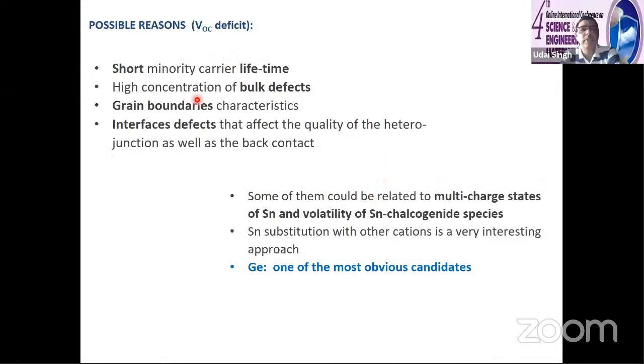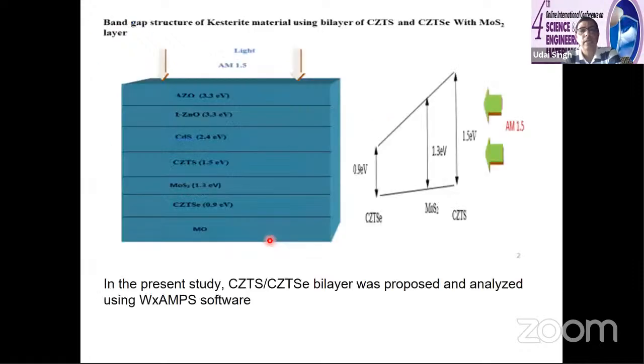There are certain limitations like short minority carrier lifetime, high concentration of bulk defects, and grain boundary characteristics. People have now tried to introduce germanium as an obvious candidate which can increase the VOC. A lot of work is being done on this, but still the efficiency has not moved beyond what we have shown earlier. In this pandemic, we have also done some theoretical work.